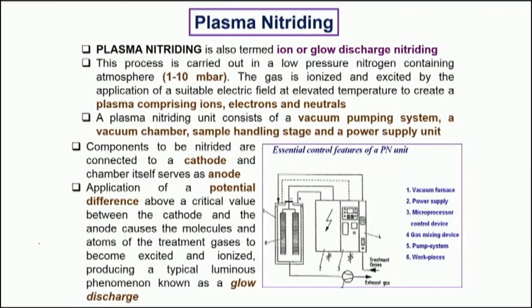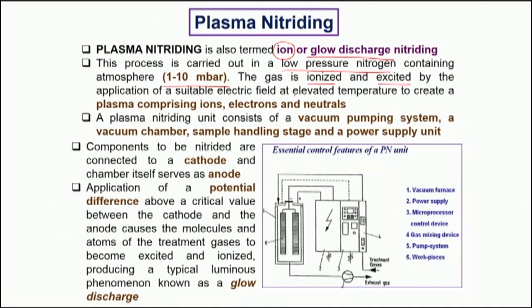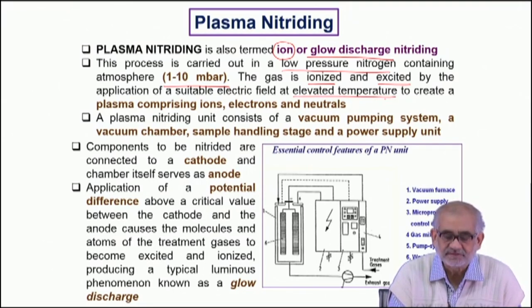The process of plasma nitriding is sometimes also referred to as the glow discharge process, because you do see a blue-violet glow surrounding the sample in the nitriding chamber. That glow comes from the presence of particular ions, particularly the nitrogen ions. In order to get the glow discharge you require low pressure — we are talking about anything like a few millibars of pressure. You evacuate, then backfill, and then ionize. The gas is ionized and remains in the excited state, and the temperature would typically be anywhere from 450 to 550°C.